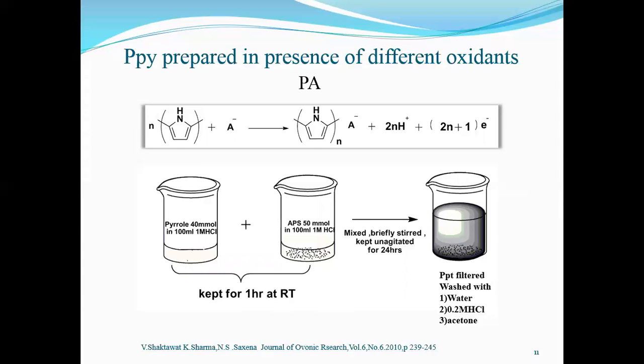On addition of enzymes, the dopant is substituted with the biological functional macromolecule via adsorption, covalent linking, etc. In this method, we have carried out chemical oxidation, that is, chemical polymerization by means of different oxidizing agents. The most commonly used oxidizing agent is ferric chloride, and sometimes ammonium persulfate, even silver nitrate, etc. can also be used. Chemical polymerization can be carried out successfully even in aqueous medium.